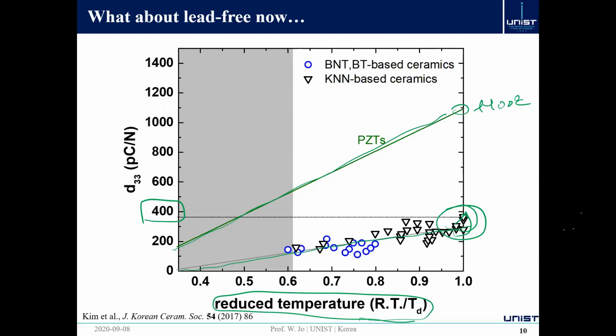First possibility would be to make a single crystal. If you work with a single crystal, it can even reach values near PZT. Of course, this is from the data I collected from the available literature, so this cannot really represent all the materials in the world, but at least it gives you some insight into the goal we can achieve. It's just helpful in better understanding what we can expect from our research activities.